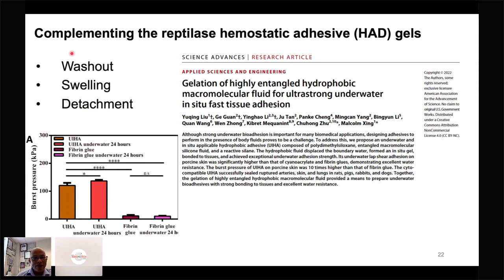So in a follow-up study, what we have done is complement the hemostatic adhesive gel, in a paper that came out also in Science Advances a couple of weeks ago, where we designed a hydrophobic, which is water-hating, material to address the swelling issue and this washout, because if it's not solubilized, then it cannot be washed out. A water-hating, highly hydrophobic in situ hydrogel for tissue adhesive. So this material functions in a very interesting way. Basically it gets into the site of the injury, displaces water at the site of the injury, makes contact with the tissue, and then it forms a strong adhesion. And therefore there is no issue of detachment, swelling, or washout.